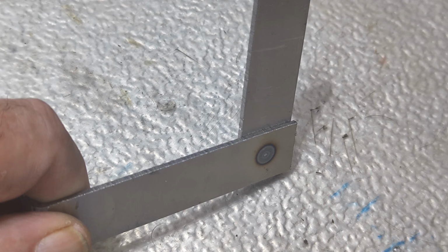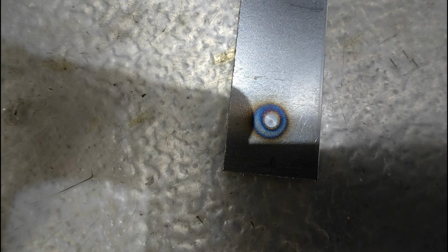Although it more or less manages to weld together two steel plates with a combined thickness of 4 mm, the available energy is clearly insufficient. The weld has not formed a proper nugget and is not strong enough. This would probably be resolved if I installed the second supercapacitor, for which I have already left space in the enclosure. For the time being, however, there is no need for it.